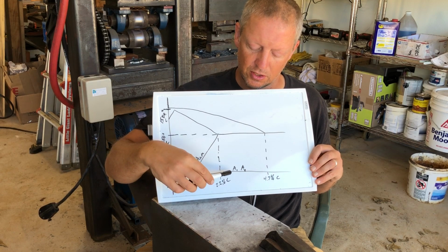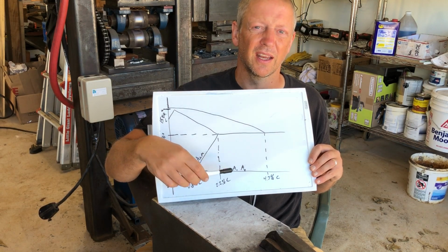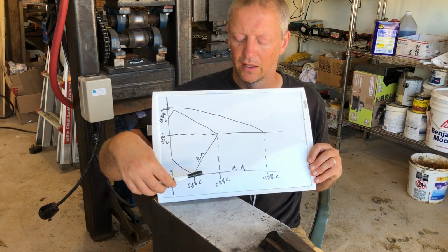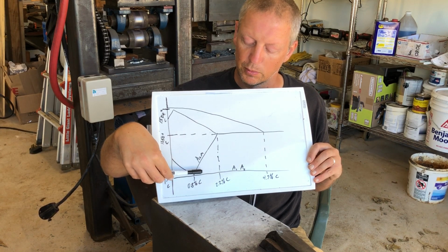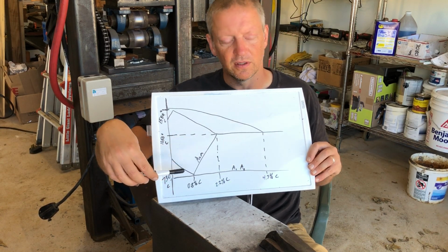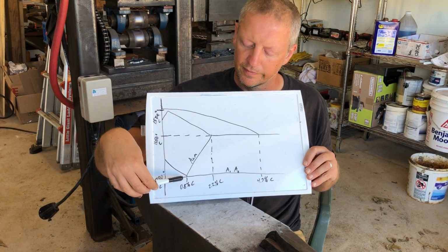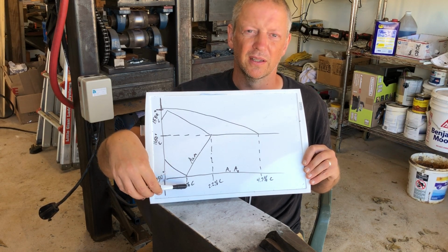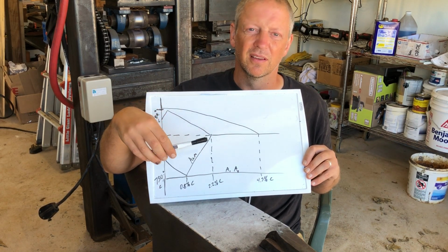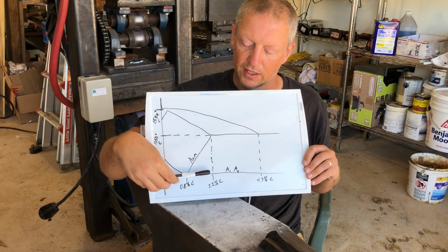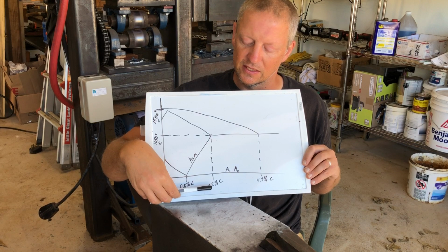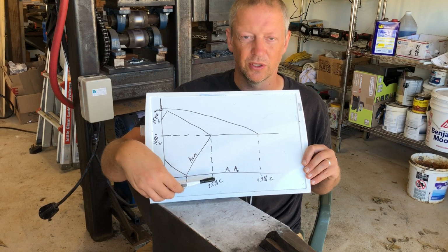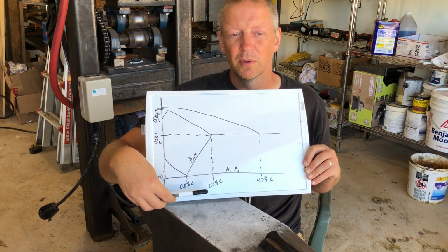And the same thing is also true, as I was noting before, for A1 and A2. Theoretically, if you were cooling incredibly slowly, let's go back to the eutectoid steel here for a moment, you'll switch immediately from austenite to pearlite. In practice, this isn't how it works. As you're cooling, you are cooling fast enough that that line is depressed. It's pushed down to a cooler temperature. So you don't actually start to transform until a lower temperature.